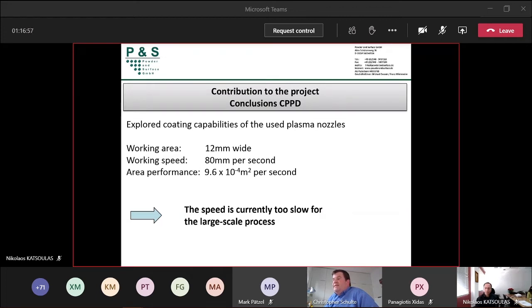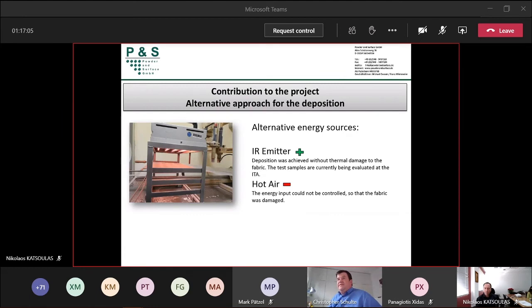And we are working to improve the heating up process by plasma with alternative energy sources. Next. Alternative energy sources, in fact, there's only one really alternative, the IR emitter. The deposition without thermal damage to the fabric is a big issue. One second, please. Preheating by IR before the CPPD had practically no effect, as the material cools down too quickly to support the plasticization. It means the way from the IR source to the plasma nozzle is too long, so it cools down, and so the effect is near zero.